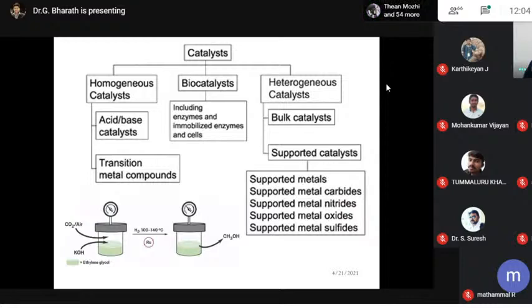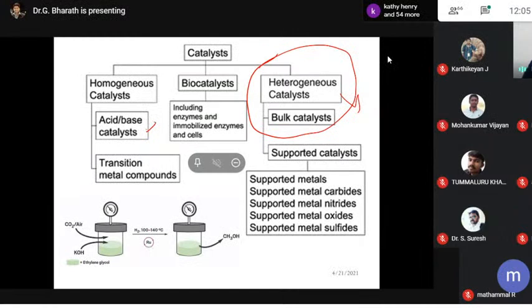So what catalysts are required? The catalysts are homogeneous catalyst, biocatalyst, and heterogeneous catalyst. In the homogeneous catalyst, importantly, we need acid-base catalysts and transition metal compounds. The biocatalyst includes enzymes, immobilized enzymes, and cells. And the heterogeneous catalyst includes bulk catalyst and supported catalyst, especially supported catalysts like metal carbides, metal nitrides, metal oxides, and metal sulfides. This heterogeneous catalyst always gives the best performance compared to the homogeneous catalyst. So why are people always using nanocomposite materials? In nanocomposite materials, especially nano hybrids, they get acid-base catalyst properties as well as metal hydride-based ones. Both properties are very important to convert CO2 into fuels. That's why people are always designing heterogeneous catalysts for CO2 conversion.